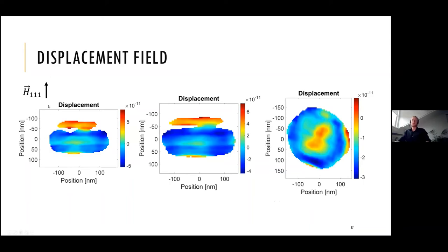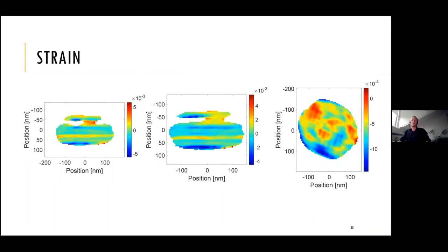And since our reflection was 111 pointed upwards, we can calculate the gradient, and then we get the strain values, which are pretty low sometimes. So we have a nice sensitivity down to 10 to the minus 4. And this is a very important aspect of the Bragg CDI, that you can access very subtle changes in the strain within the three-dimensional object.